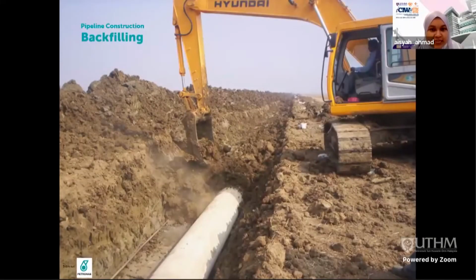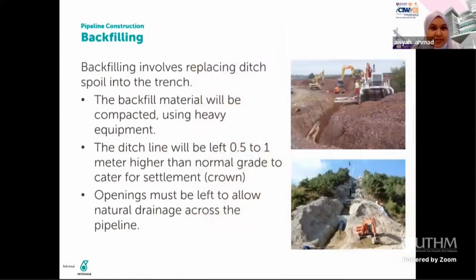So we have come to the end of trench construction for the pipeline. We need to backfill the trench, as you can see in this picture. It involves replacing our spoils, the soil we dug out before, into the trench. It will be compacted using heavy equipment. And normally we have a ditch line about 0.5 to 1 meter higher than normal grade to cater for settlement. The crown itself is about 1 to 1.5 meters. And openings must be left to allow natural drainage across the pipeline.